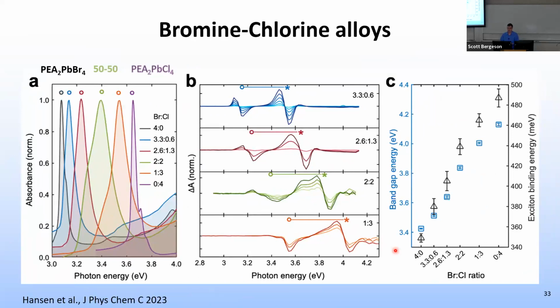We were also able to look at bromine, chlorine alloys and some other alloys also, and see here is a plot of the ratio, and then the binding energy increases with the amount of chlorine, and then the band gap also increases with the amount of chlorine. So we can tell that in between complete bromine and complete chlorine, we are getting some good alloying such that the properties are kind of the average of the two extremes.